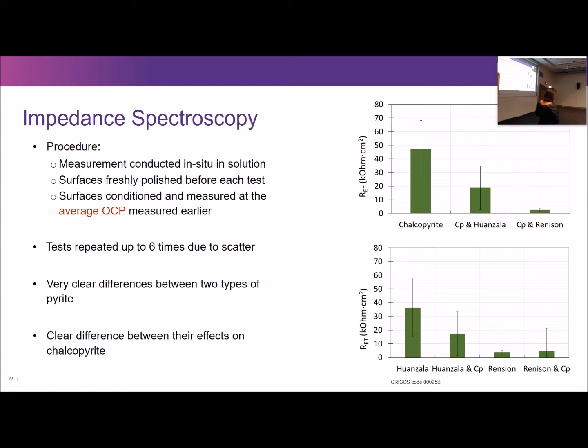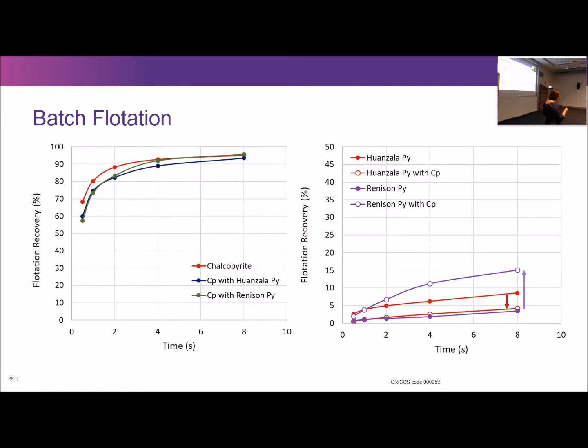When you look at the pyrites themselves, the Pyrite's resistance is initially lower than that of Chalcopyrite, but it's still relatively high. When mixed with Chalcopyrite, its resistivity goes down. You expect it to go up because we know that pyrite floats better when in the presence of Chalcopyrite, but this one's going down. So that was a little bit strange. Whereas the Renison pyrite resistivity was very low, very close to 0, and because of the high variations, I couldn't actually tell whether the couple with Chalcopyrite was higher or lower. It was entirely within the error range. So that was a bit inconclusive, but I would have expected this to go up. So let's see what happens with the flotation data. In the flotation data, the red line is Chalcopyrite, which floats beautifully on its own, we all know this.